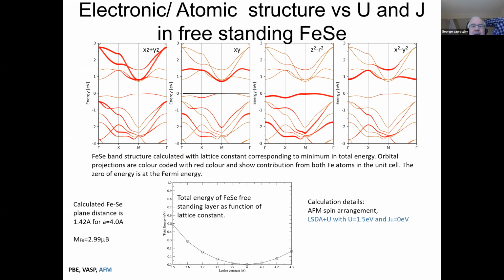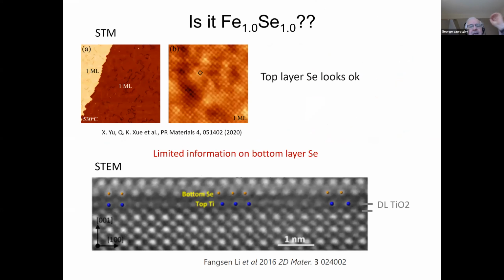Okay, so we then were looking at other things that might happen. For example, the top layer, the top selenium in this STEM data down at the bottom, but also from the very beautiful surface truncation rod experiments that Kazhu did, they showed that the selenium actually is not symmetric. The iron is not symmetric between the two selenium layers. The layer at the bottom is a little bit closer to the iron than the layer at the top, the selenium at the top. Okay, so we tried that, but that doesn't really do much to the band structure actually,